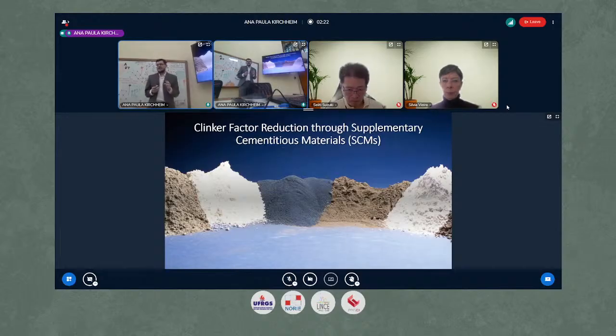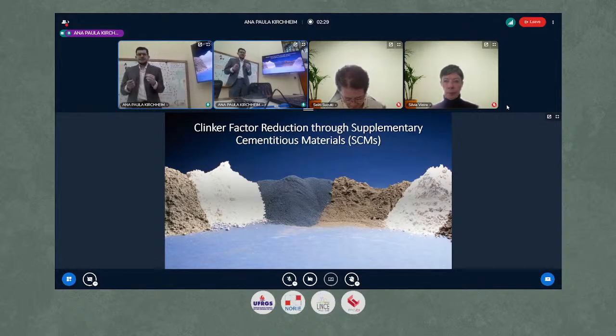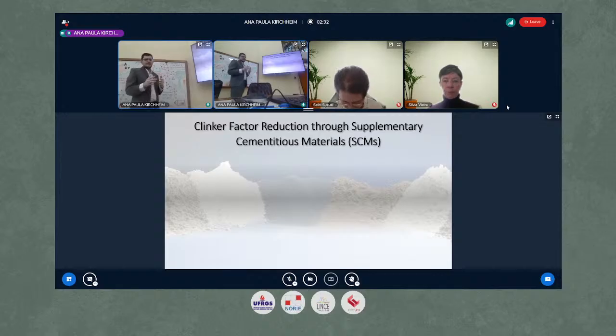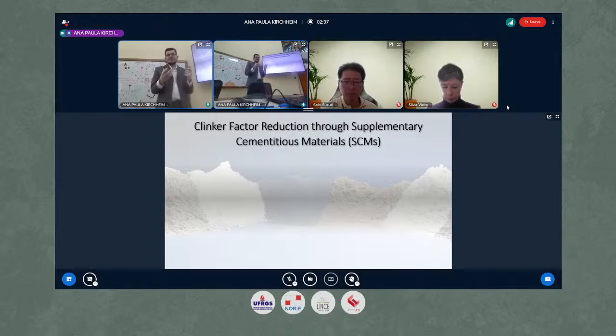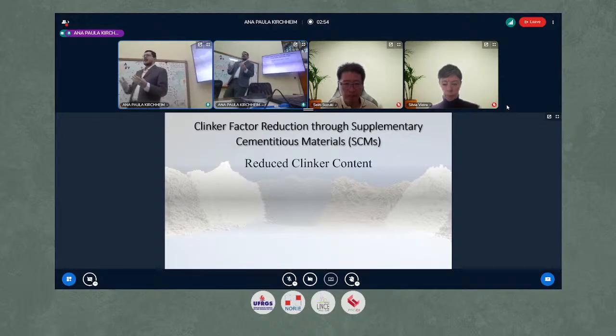Another straightforward strategy is to reduce the clinker factor through the use of supplementary cementitious materials. So we want to reduce the clinker, which is the fraction that emits the most CO2, by using calcined clays, slags, fly ash, and limestone filler. Every time more SCM and less clinker. So we are achieving reduced clinker contents. We are talking about something like 30%, 35% of clinker.